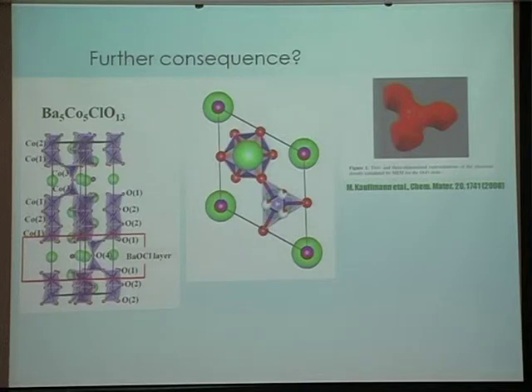Now, how can this happen? This can happen in 2 ways. One way is within the experimental time scale of diffraction, if this particular oxygen is fast moving between these 3 positions, diffraction will give you this information. Or there is another possibility: that oxygens are not moving within that time scale, they are static. At one site, oxygen is fixed here, in some other site it's fixed there, and somewhere it's there. So on average, it says 1/3 here, 1/3 here, 1/3 here. Now, this is the problem of an average probe.